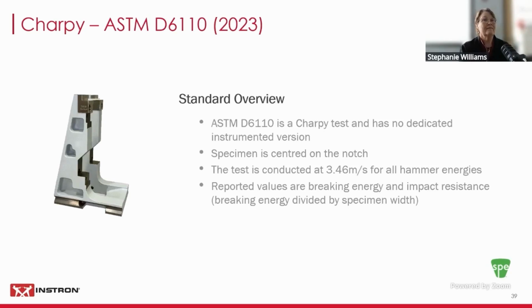The overview, there is no dedicated fully instrumented version in ASTM. As I noted, the notch specimen centered on the notch. The test itself, regardless of the amount of impact energy you're using, so whatever the capacity of the hammer is, the testing is always conducted at 3.5 meters a second. What you're reporting are the values, the breaking energy and impact resistance. So this is breaking energy that's divided by the specimen width. ASTM defines a Charpy to D6110.